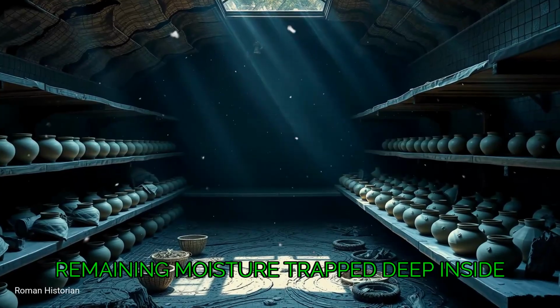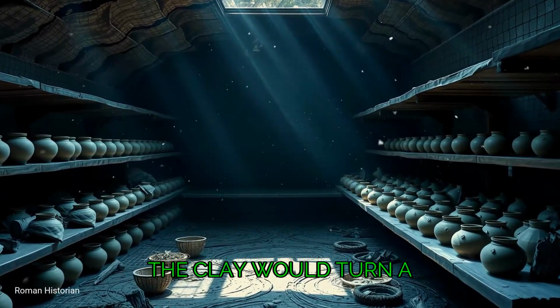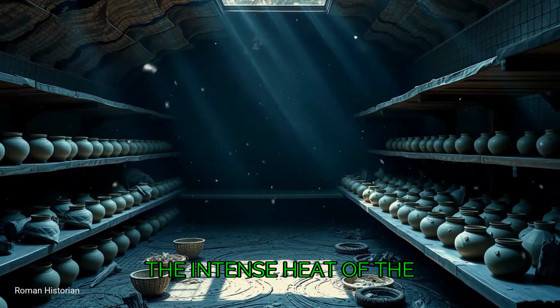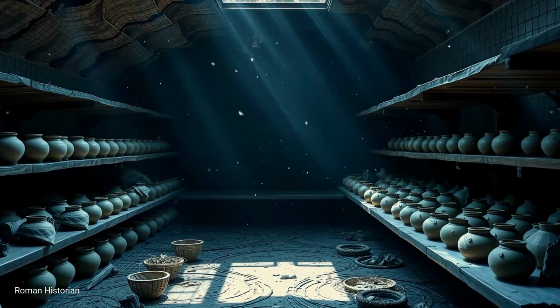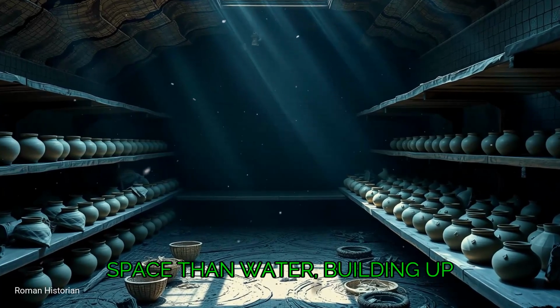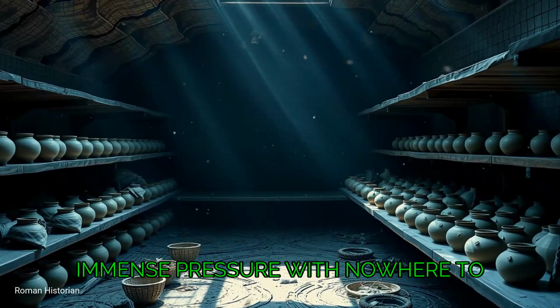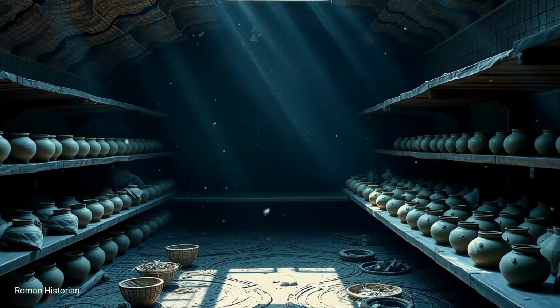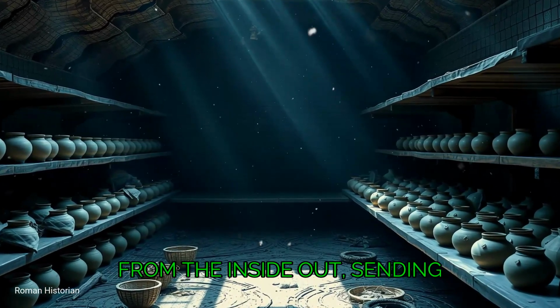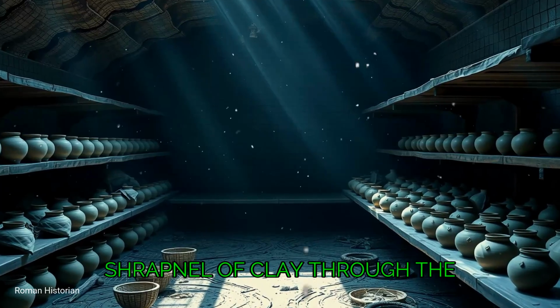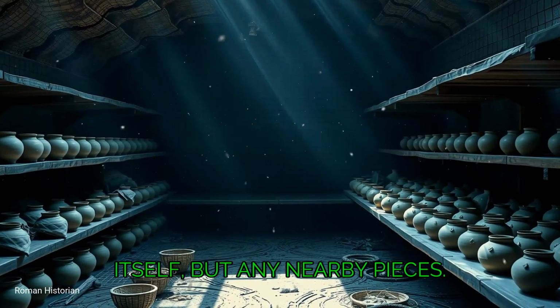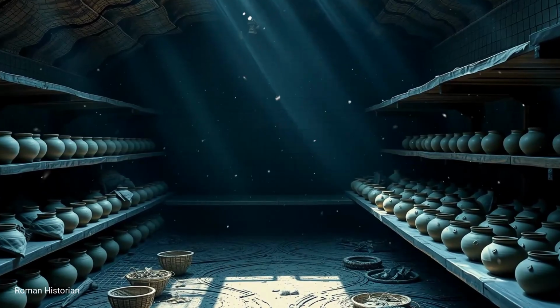Any remaining moisture, trapped deep inside the clay, would turn to steam the moment it met the intense heat of the fire. Steam takes up far more space than water, building up immense pressure with nowhere to escape. The pot would literally explode from the inside out, sending shrapnel of clay through the kiln and destroying not only itself, but any nearby pieces.